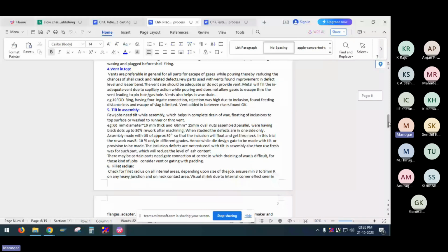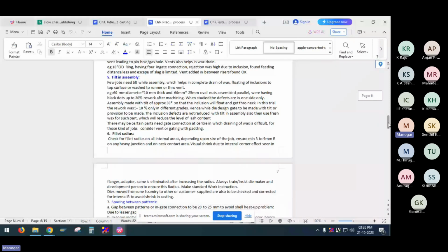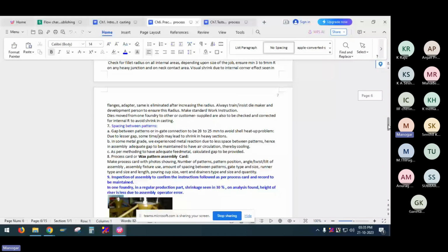Then the fillet radius we discussed in the die design. If you give a proper fillet radius and avoid sharp corners, then we are avoiding internal corners, which avoids visual shrinkage in the castings. And spacing between patterns we also discussed in the assembly. That is a must for having a proper cooling area. And in some alloys, when there is no proper spacing or no air gap between the shells, a metal-mold reaction takes place. So it is a must to have proper spacing between the parts in the tree assembly. Also, spacing is required to have proper feed metal through the runner for the particular component. Otherwise, there is a chance of shrinkage if there is no proper space to feed metal from the runner.